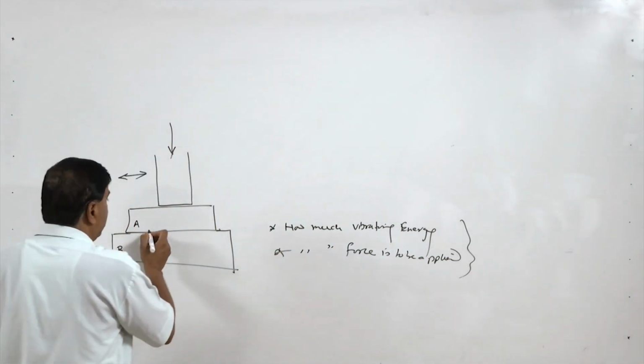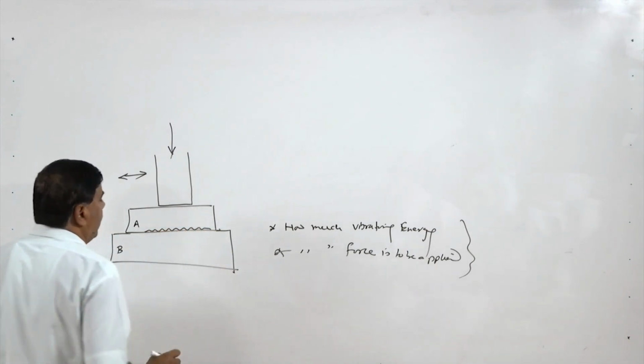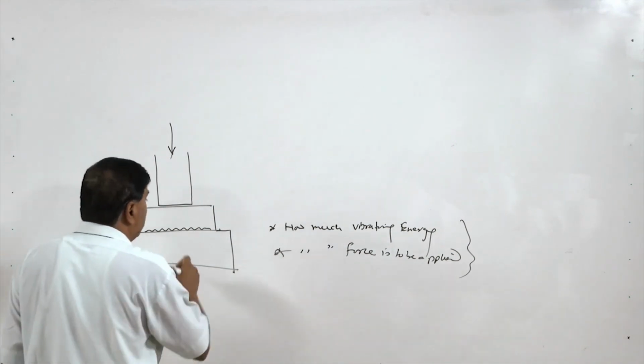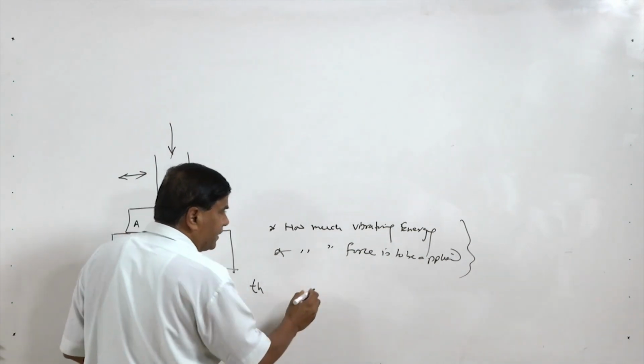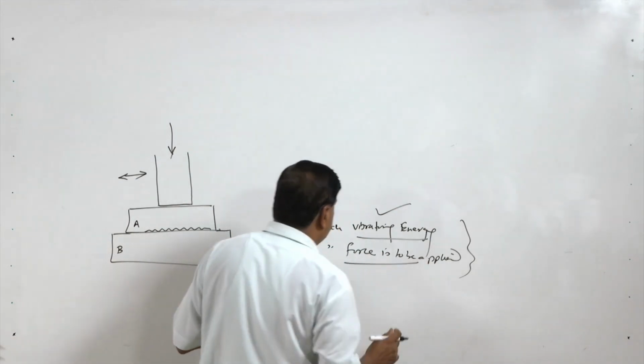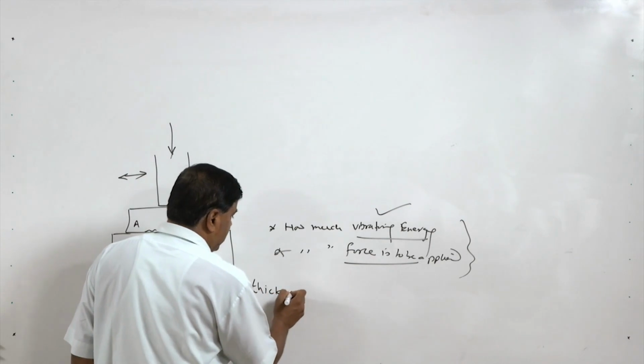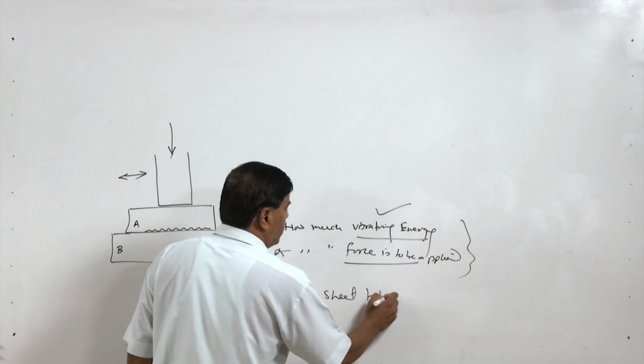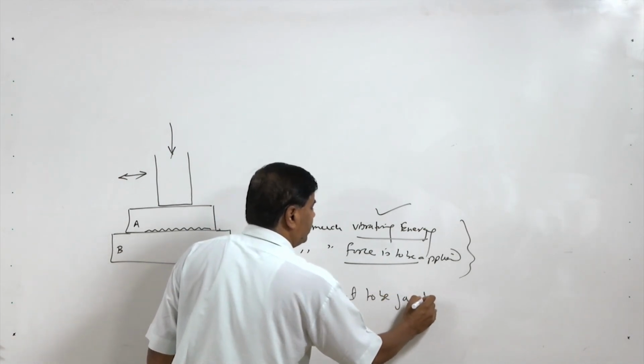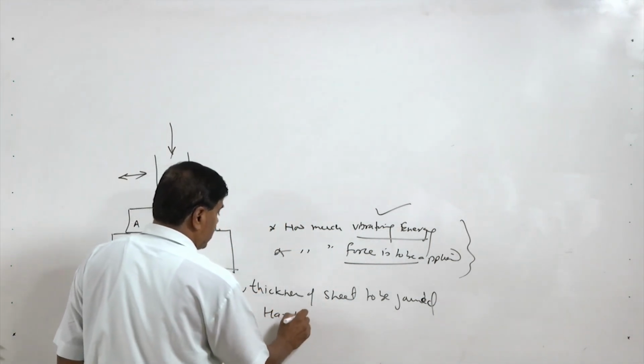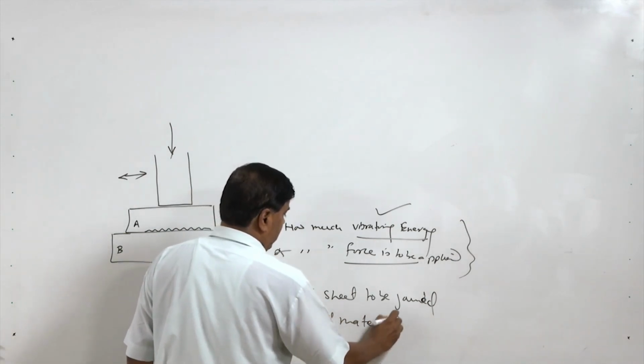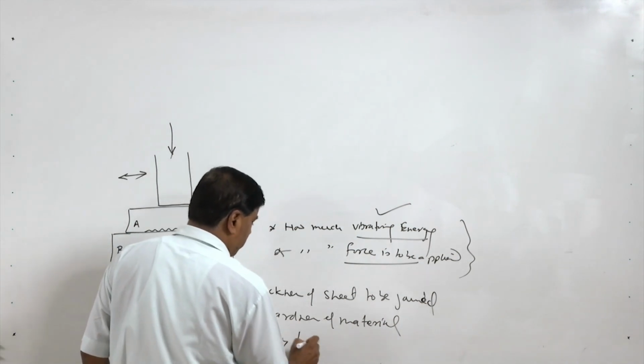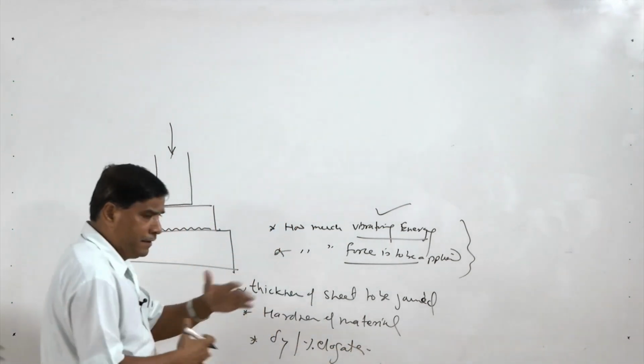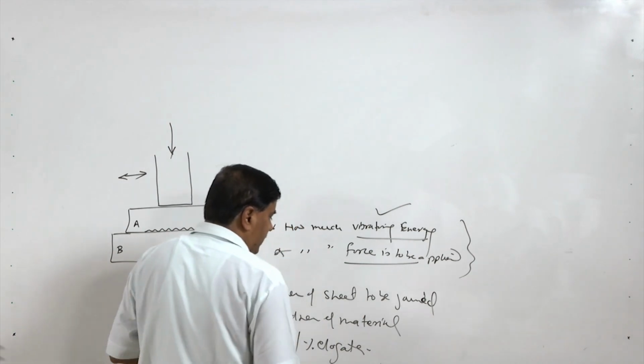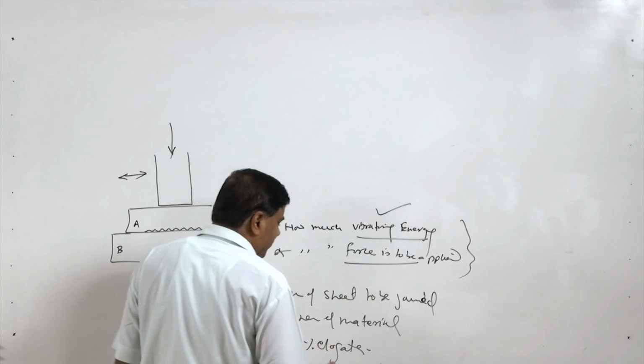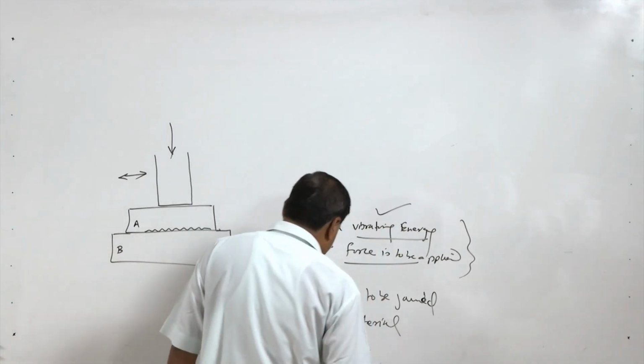So, what is important here? The kind of surface conditions, like surface roughness, presence of impurities, hardness of the material. The factors that affect these two, vibratory energy and the clamping force to be applied, are influenced by the thickness of the sheets to be joined, then hardness of the material. Then yield strength and percentage elongation also to some extent determine the plastic flow behavior of the material at the interface during the process. So, these factors also affect the amount of energy that it will take before development of the sound weld joint, apart from the presence of impurities and oxides, etc.